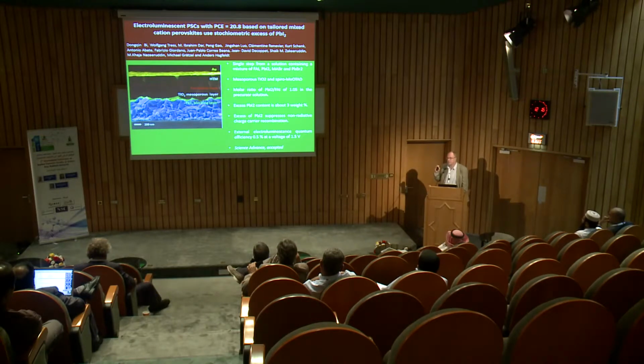It decreases recombination processes that we know. We see an increased photovoltage with this lead iodide excess. We see higher luminescence, so the emissive recombination increases. So it suppresses non-radiative recombination.